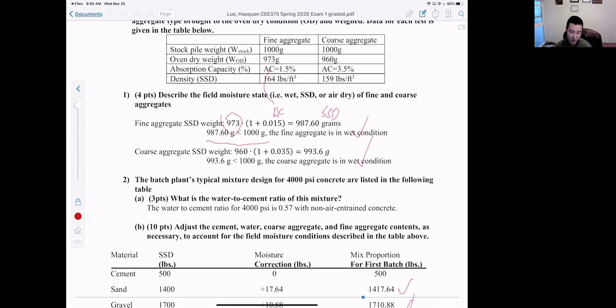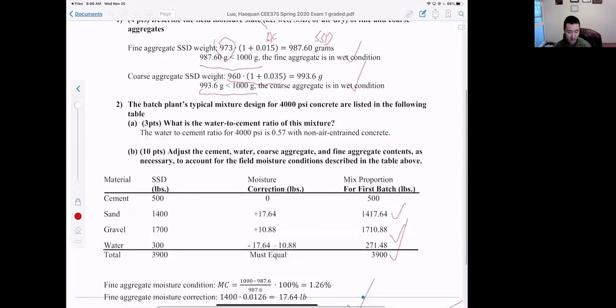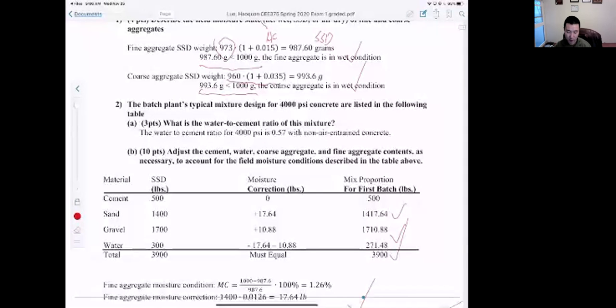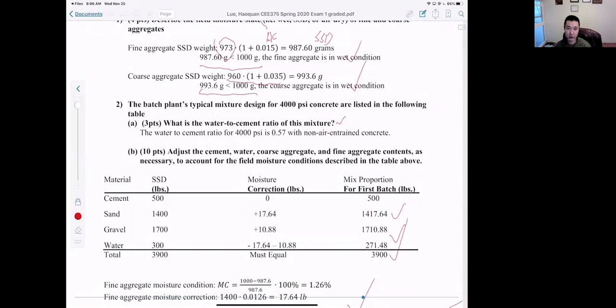For coarse aggregate, again we do this. The SSD weight is again smaller than the stockpile weight, so the coarse aggregate is also in wet condition. The next part asks what the water to cement ratio of the concrete is. Remember, the water to cement ratio does not change depending on the moisture condition of the coarse aggregate and the sand. That's the exact reason we do the moisture correction. How to calculate the water cement ratio is very simple. We just use the weight of water divided by the weight of cement.